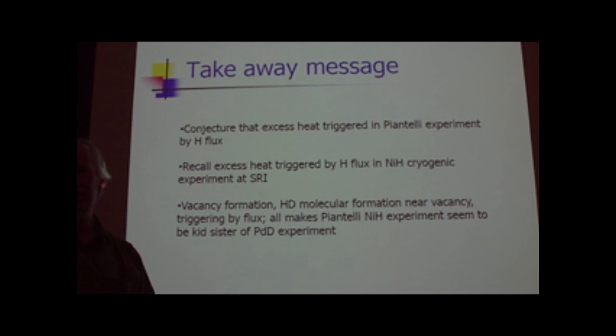Piantelli seems to argue that the effect occurs very near the surface, and the surface gets really beat up. He's published photographs of the surface, and it just looks like somebody's come in and bashed the heck out of the surface. Really? But it doesn't decrepitate? It doesn't fracture, or decrepitation, where material under hydriding actually comes apart over a period of time and flakes off. I don't know that that's observed or not observed. I know that the surface looks discolored, beaten up, with non-uniformities on the surface, places where it looks like the surface was gouged. But I don't know if that's due to the effect of nickel.